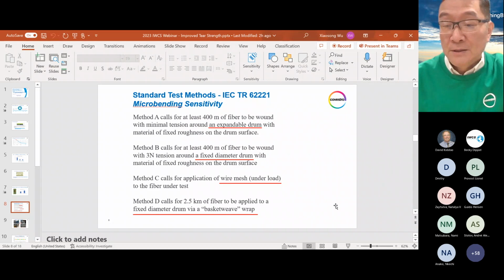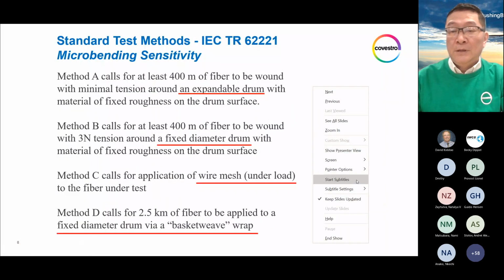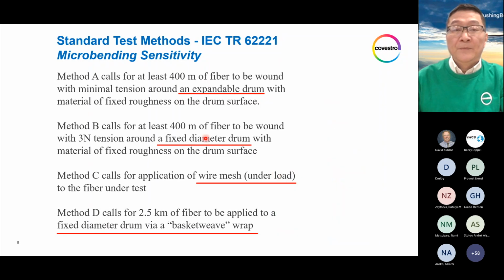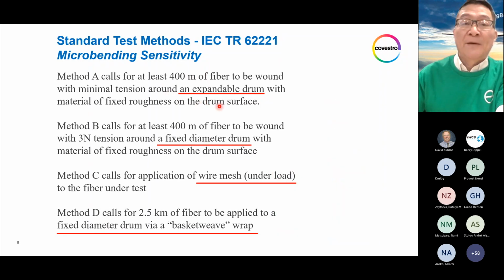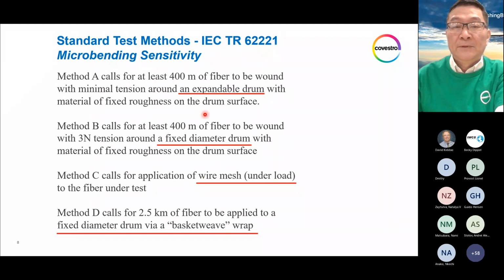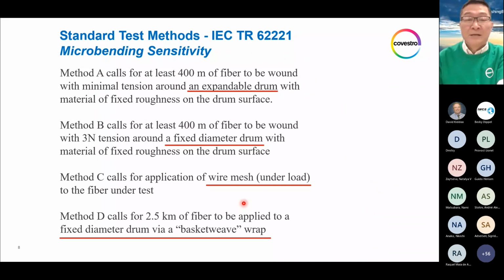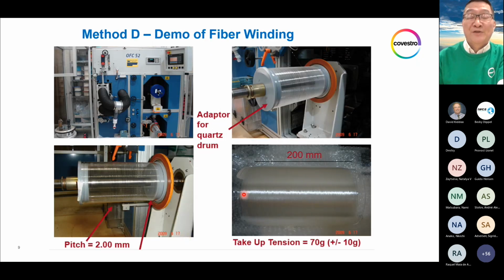So now I'm going to put it back to the slideshow. There are 4 official test methods by IEC technical report 62221 A, B, C, D. They use different drum sizes, and some even use wire mesh or sandpaper to create lateral force. However, there's one method called method D, which utilizes a basket weave, which means you wind the fibers just like a basket weave, to create a fiber-to-fiber interaction to simulate.